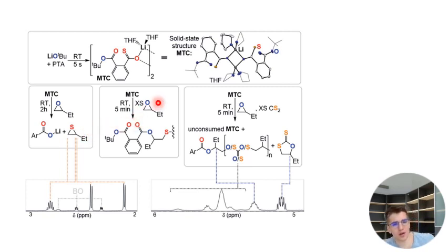When you did this not stoichiometrically with epoxide but with an excess, you could then actually see that this rearrangement, right, and the epoxide inserted here, and it rearranged to form an ester, right? Although you had a sulfur initially at the aromatic unit, when you reacted this species with an excess of epoxides, you only formed esters, which confirms this exchange reactivity of the species after epoxide insertion by the trithiocarbonate, and then similar things were observed when you had some CS2 present.